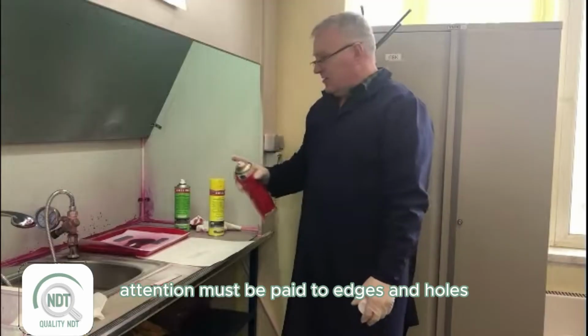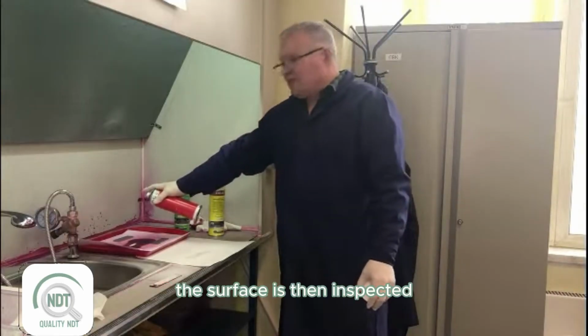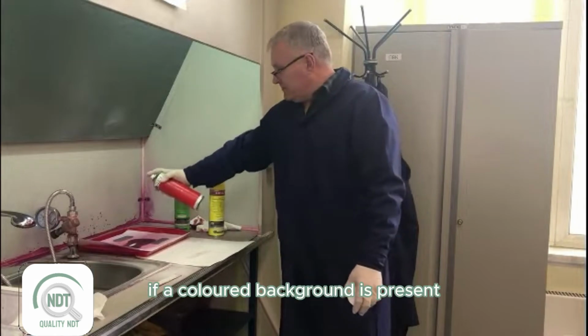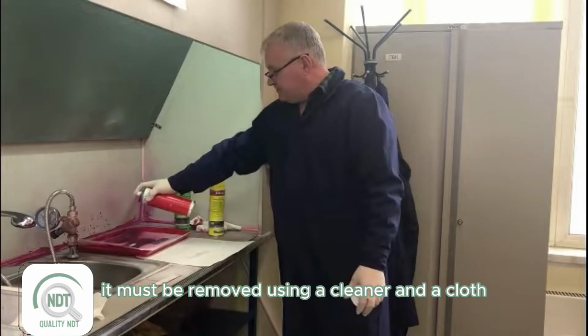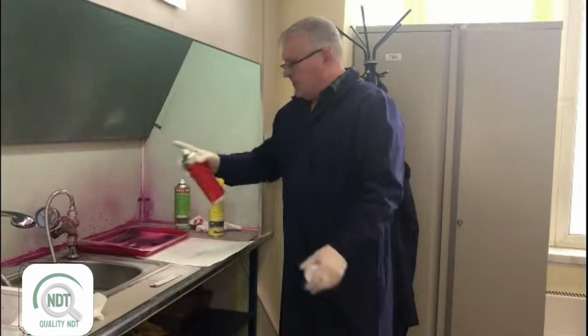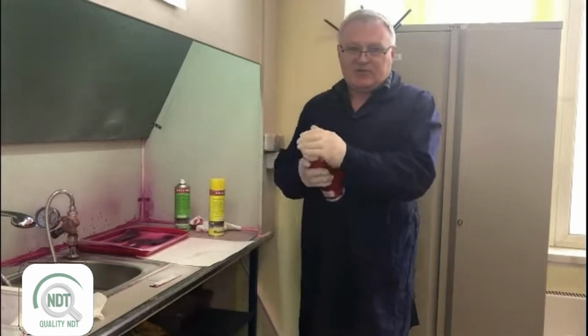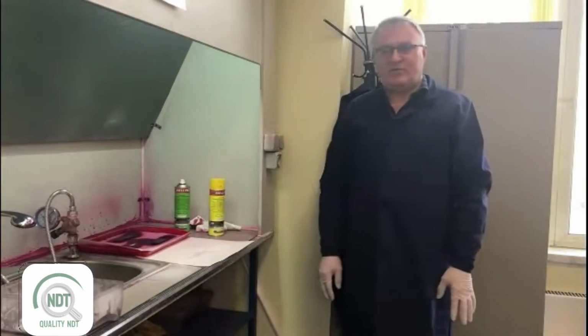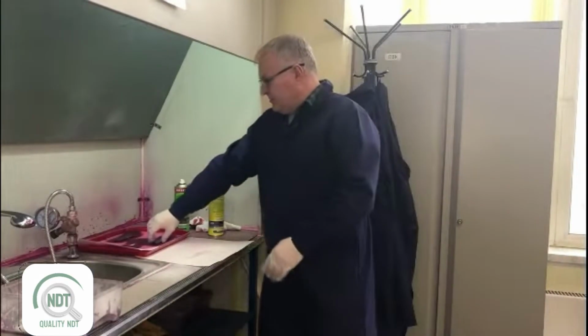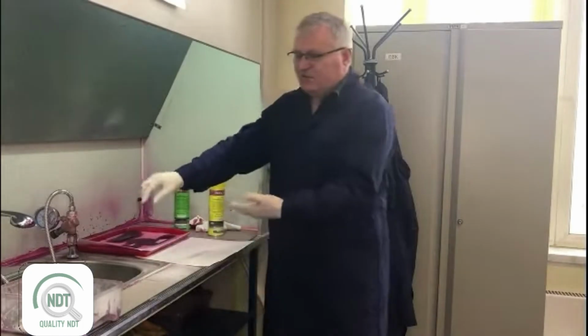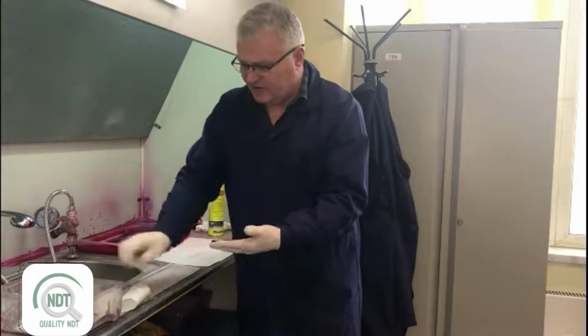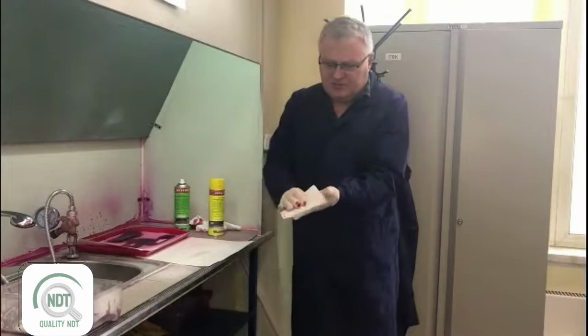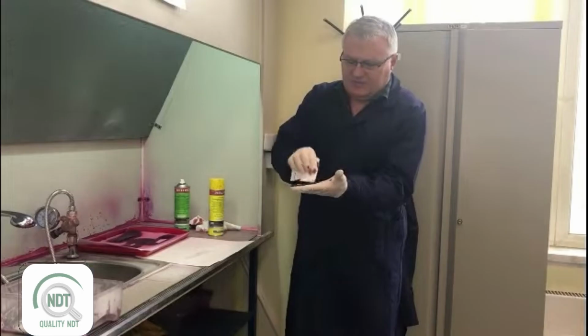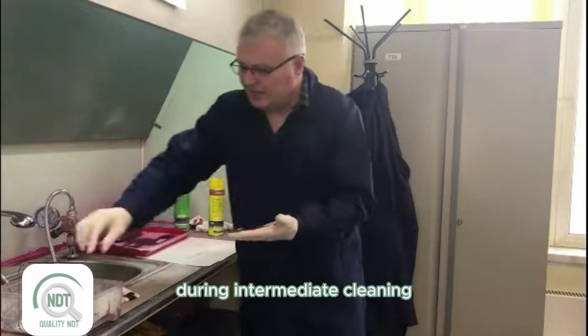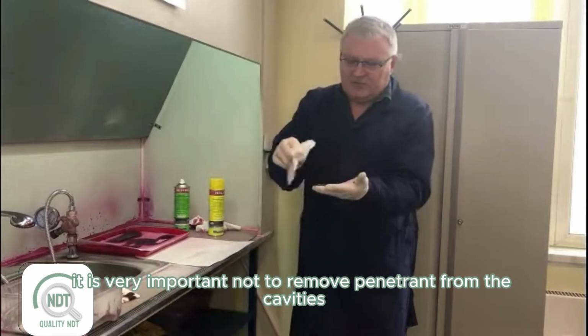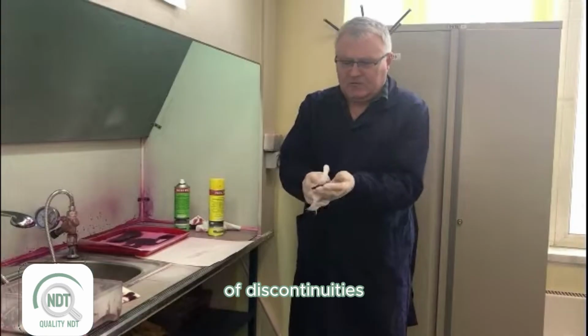Attention must be paid to edges and holes. The surface is then inspected. If a colored background is present, it must be removed using a cleaner and a cloth. During intermediate cleaning, it is very important not to remove penetrant from the cavities of discontinuities.